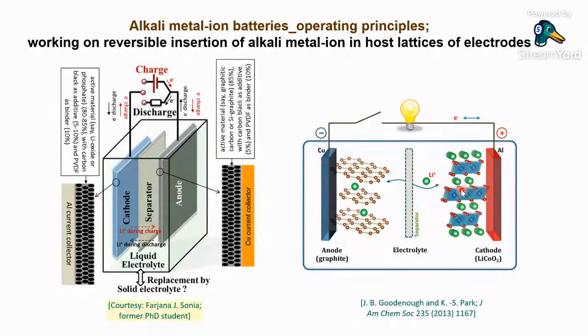So this insertion and removal cause a lot of changes to the electrode material. They end up changing the structure of the material in many cases, which can be good or which can be very bad. Which in turn renders this very fascinating to look into from a material science perspective. And of course, in addition to that, a lot happens at the electrode electrolyte interface, which needs to be understood and engineered to have a good